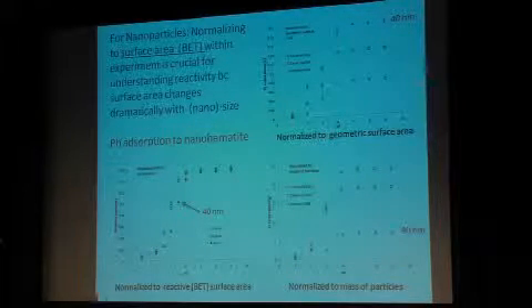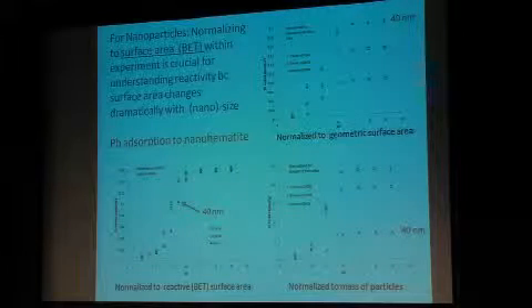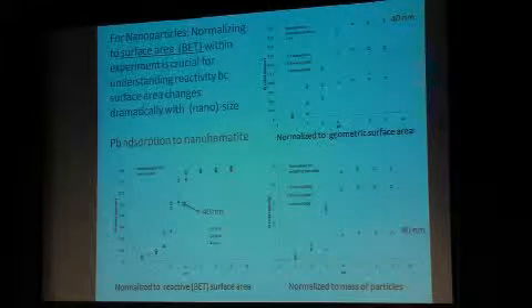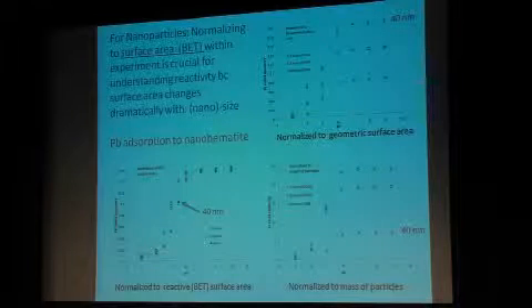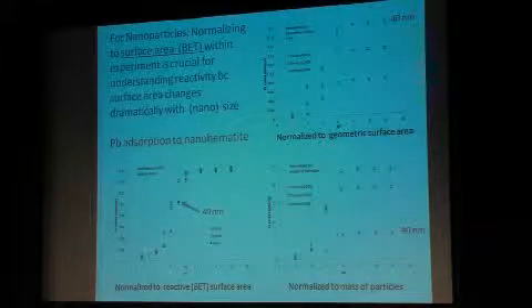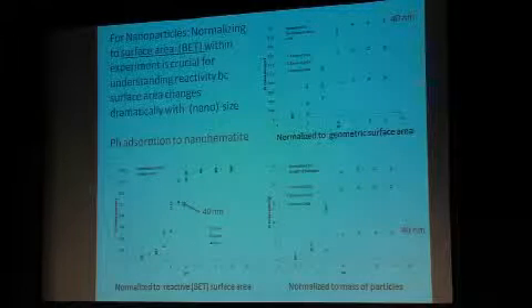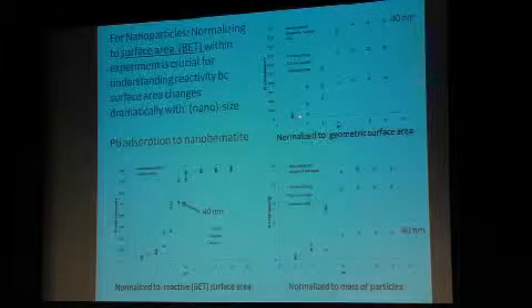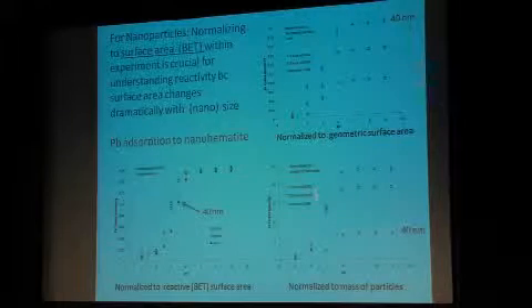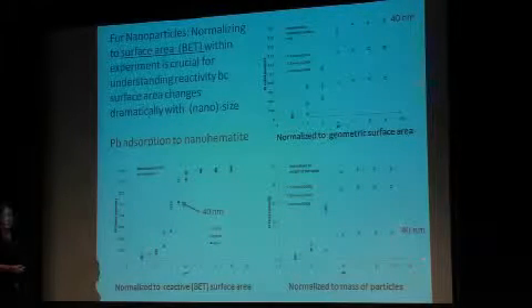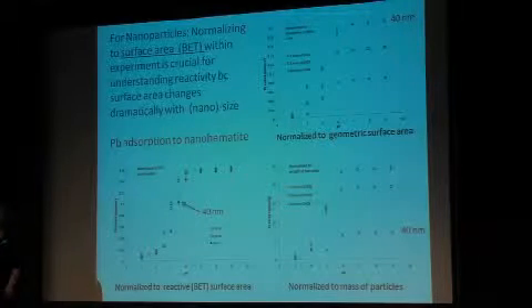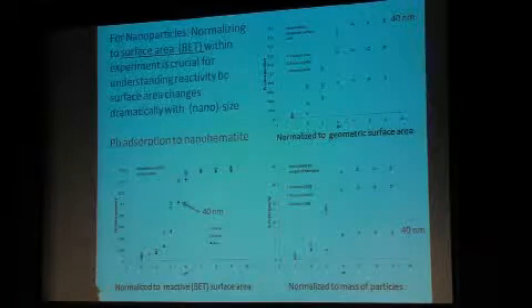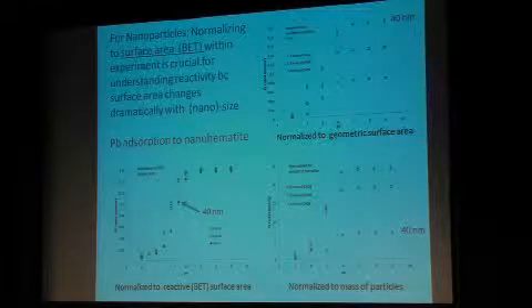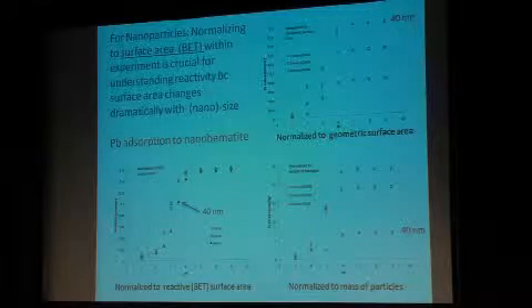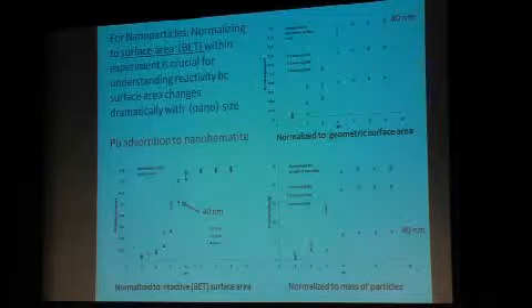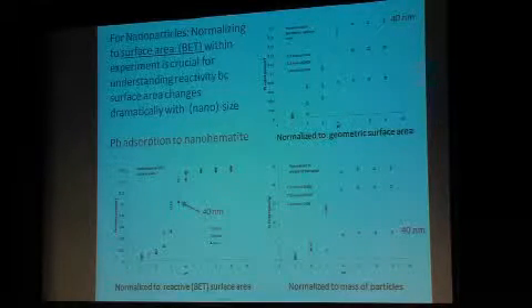We ran this experiment normalized to take account for the differences in surface area. Usually when people run experiments, they put the same number of grams of the materials in. For nanoparticles that have huge differences in surface areas, that makes a big difference. This is what the results look like if you normalize to geometric surface area. This is what the data look like if you normalize to the mass of the particle. The effects of the nanoparticle size become completely different depending upon how you normalize your experiment, because surface area changes so drastically with particle size when you're small, and you're running a different experiment if you're not normalizing to surface area but to mass.